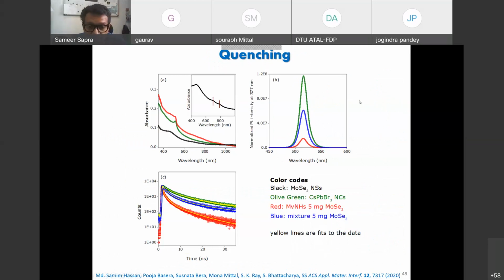What happens also is that there's a fluorescence of cesium lead bromide at about 515 nanometers. And when you attach the two with ATP, the fluorescence is quenched, because the charges migrate from the perovskite to MoSe2. When you just throw them in solution without ATP, it is also quenched, but not to such a large extent. So you know that these are really attached particles. Also, if you look at the time resolved fluorescence, the same quenching behavior can be seen because the fluorescence lifetime becomes much shorter in case of the attached particles.